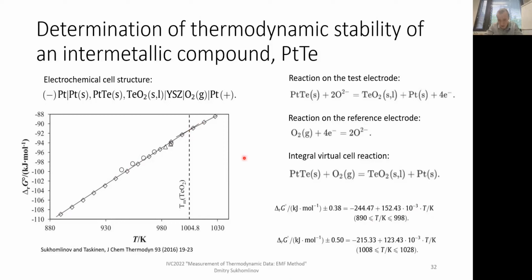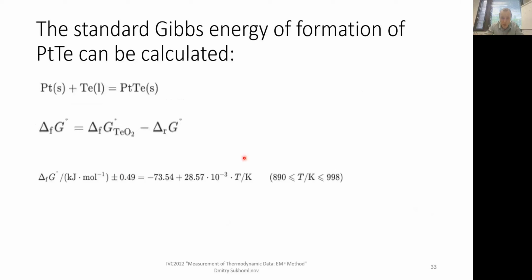But our ultimate target is to determine the Gibbs energy of formation of platinum telluride. So we are not yet there. But in the previous example, we measured delta G of formation of tellurium dioxide. So we just need to combine the one we measured with the Gibbs energy of formation of tellurium dioxide. We actually subtract one from another. And that gives us what we want: platinum solid plus tellurium liquid giving platinum telluride. That's the expression.